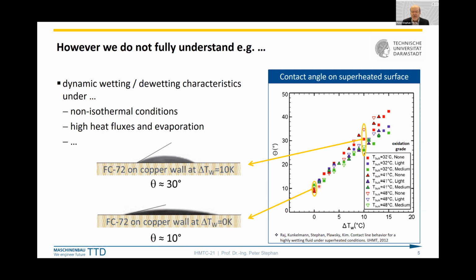However, if we increase the wall superheat, the contact angle that we measure is increasing. So even though this is quasi-static, in this situation we measure 30 degrees. A quite big difference when jumping from isothermal conditions to 10 Kelvin superheat, from 10 to 30 degrees contact angle.